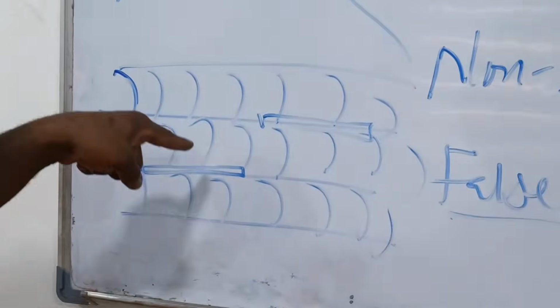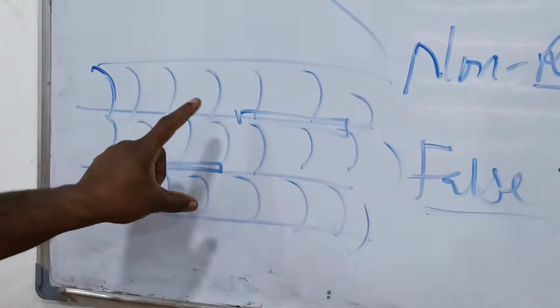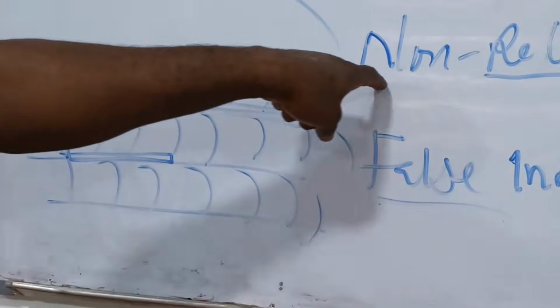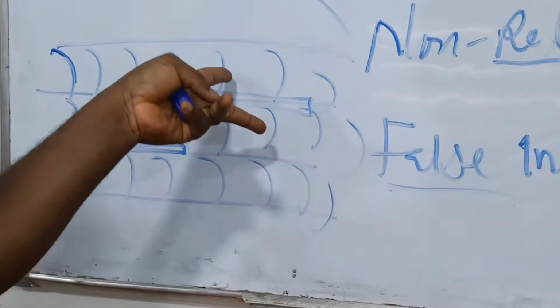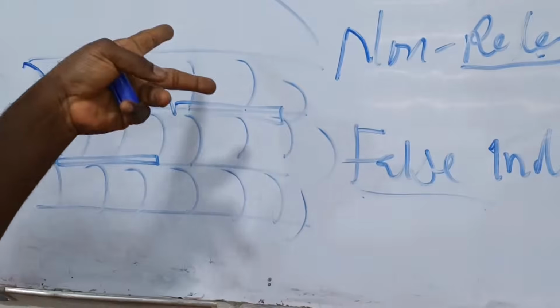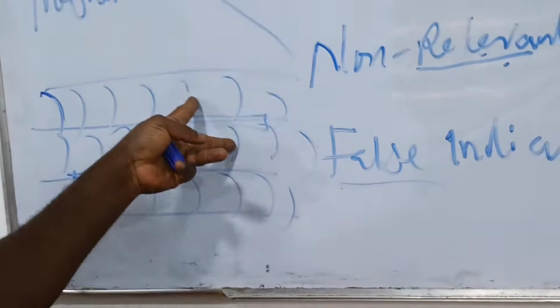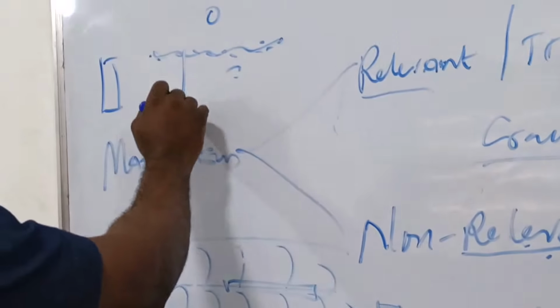This is not a defect indication, but it is caused by the geometry of the material we are checking. So that becomes a non-relevant indication. But it is the magnetism that is attracting these particles to this point, thereby causing this indication you see. But it is non-relevant.